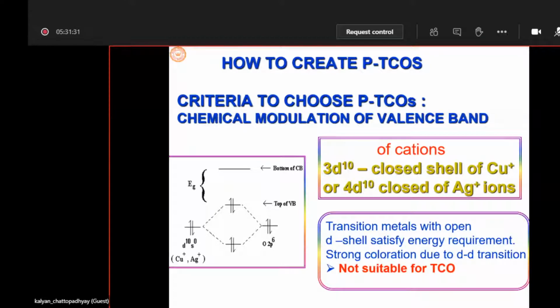That means we have to find some element which has an orbital with energy equivalent to the oxygen p orbital, and then if we can alloy this orbital, we will be able to disperse the valence band. We will be able to create a larger volume of the valence band, and then if we can introduce some doping, the holes will have enough space so that under the application of a small electric field, they can move easily, or we can expect to decrease the effective mass. So this is the so-called orbital alloying technique, or chemical modulation of valence band technique.